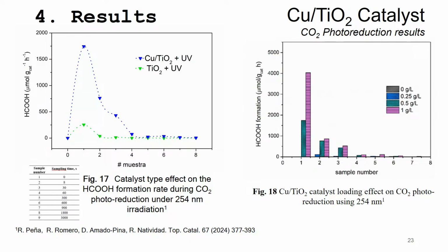Because the higher the catalyst loading, it produces this screen effect, which affects the photons reaching the higher distance from the axis of the reactor. So be very careful about this variable. We obtained here that with 1 gram per liter, there was the highest concentration. We obtained also the highest concentration of formic acid. However, this catalyst concentration is quite high compared to the catalyst that we use.